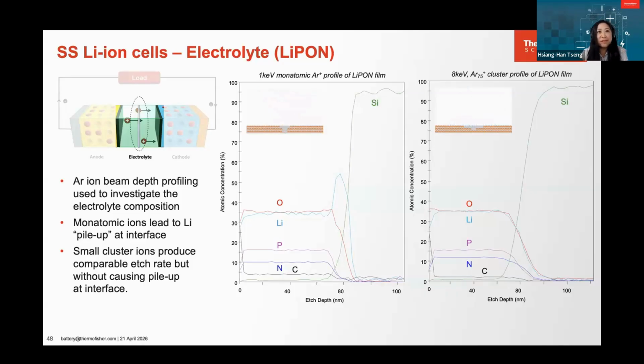The reason we are getting this kind of behavior can be explained by the monatomic beam basically pushing the ions. As the lithium ions hit the interface, they couldn't go any further. So that's why you get a small increase just on top of the substrate. On the right-hand side is the result when we use cluster ions. And it's true that we no longer have this kind of damage, and the profile is more accurate now.